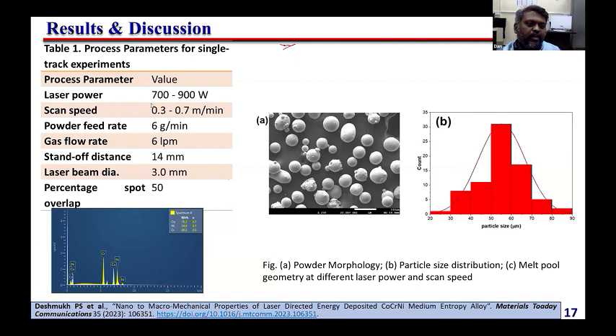These are all the parameters we used. There are different laser powers we tried, and also different scan speeds in the DED system. We tried to vary between 700 to 900 watt, and scan speed we kept between 0.3 to 0.7. Remaining other parameters we kept similar: powder feed rate, gas flow rate, stand-off distance, everything we kept very similar.